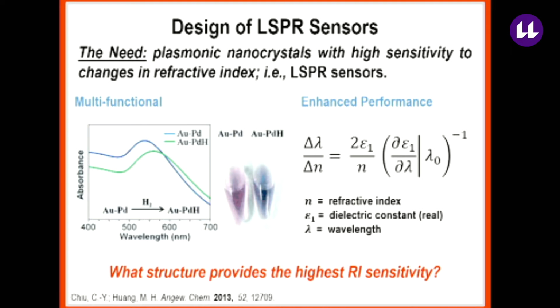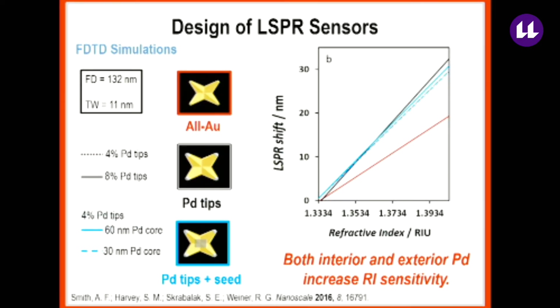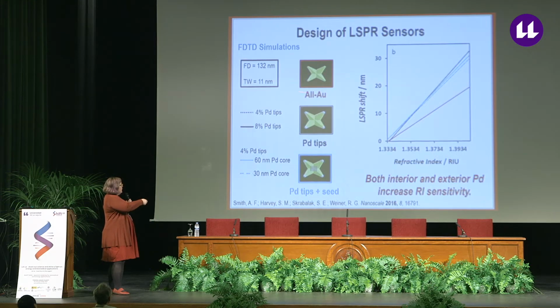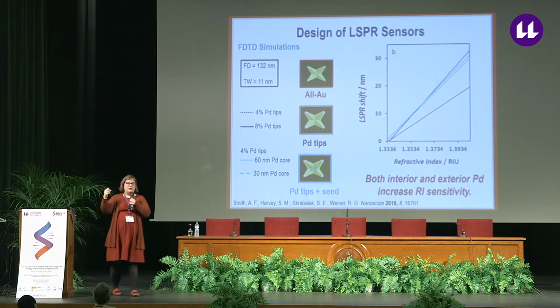And to try to tease this out, we turned to computational tools and built models of our nanocrystals and applied finite difference time domain simulations to these nanocrystal models in different refractive indices to identify what types of structures were going to be most sensitive to changes in environment. So we built all gold nanocrystals. We also took gold nanocrystals and put palladium just at the tips of the nanocrystals.